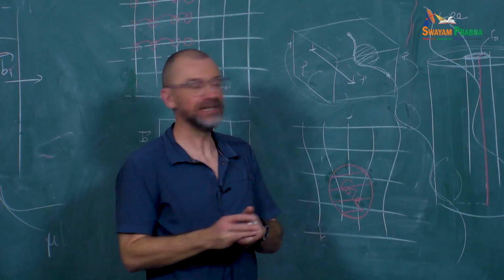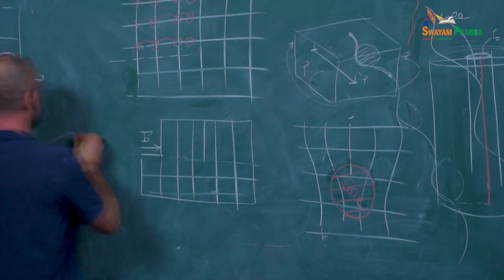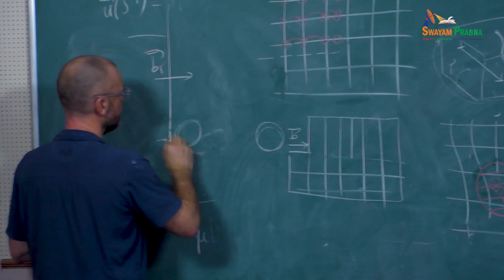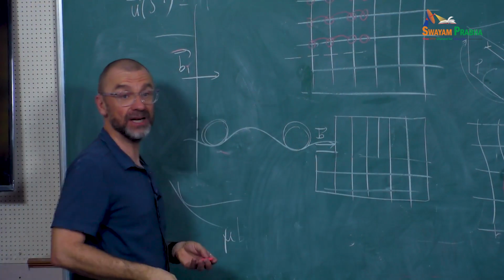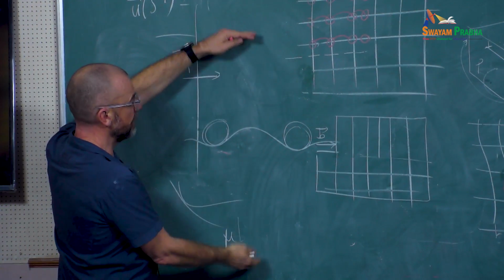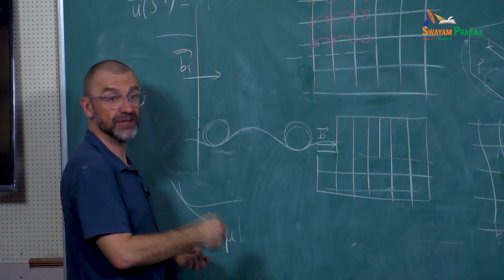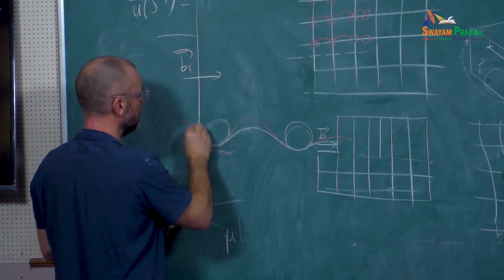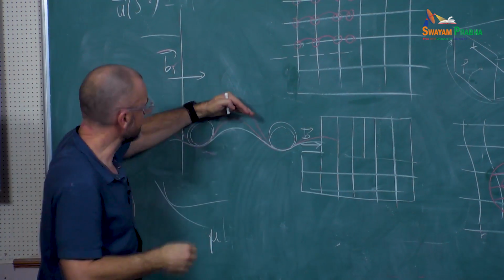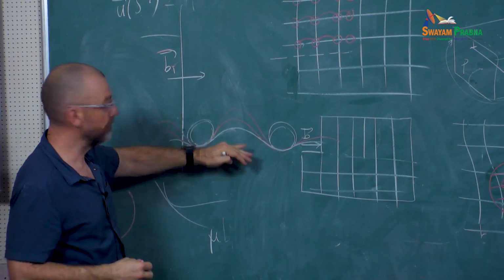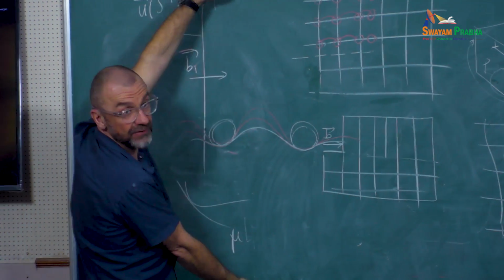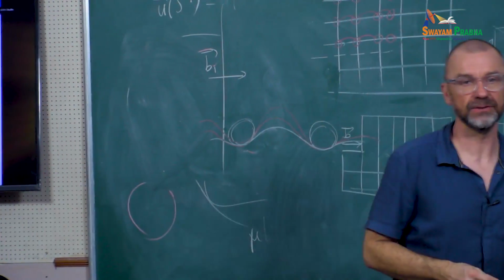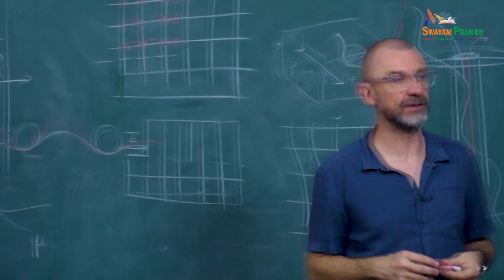And so what we have seen is that if I have my two obstacles and the dislocation is bowing like this in my simulation, and I make the simulation bigger and bigger to decrease the interactions, what I see is that the bowing out will increase, and will increase more and more. At some point it will stop, but I know that the bowing out will increase if I make the simulation cell bigger and bigger. That's because of the interactions between the two dislocations, between the infinite number of dislocations.